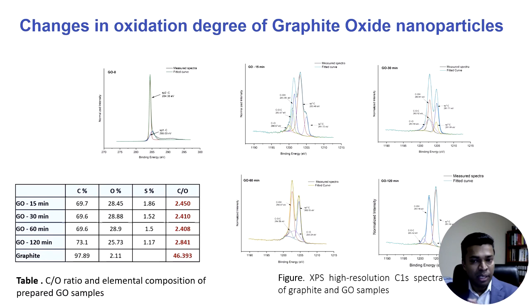If we add graphene, yes, it will improve the properties in the same way as graphite oxide. But in our case, we don't need the single layer graphene. So we did the oxidation for graphite and converted the graphite into graphite oxide. Basically, the meaning of graphite oxide is we have multi-layer graphene. So instead of one layer, now we have four, five, six layers together, but still significantly lower density than the original graphite.